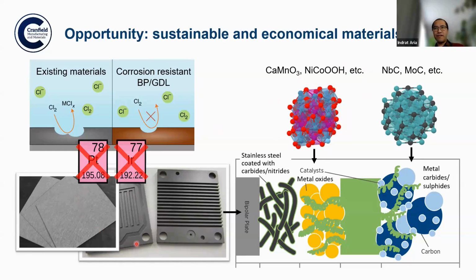And with the same material, we are coating the bipolar plate and the gas diffusion layer to basically prevent corrosion. Corrosion usually happens if the water is not 100% pure. You have chlorine, right? So chlorine comes from salt. It's everywhere, especially if you use salt water or you have salt seeping from the soil. So the chlorine will attack, and if you have steel, this will corrode the steel very quickly. This is the reason traditionally we use platinized titanium. Our goal is to replace this platinized titanium by carbide or nitride stainless steel. Stainless steel is cheaper than titanium.